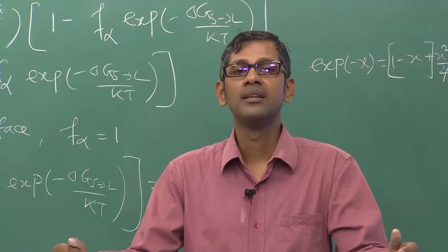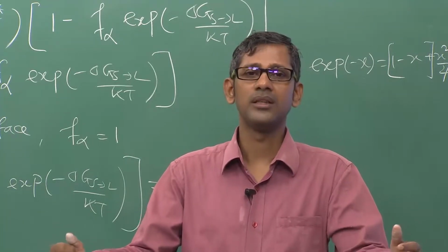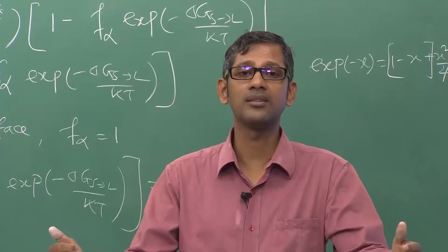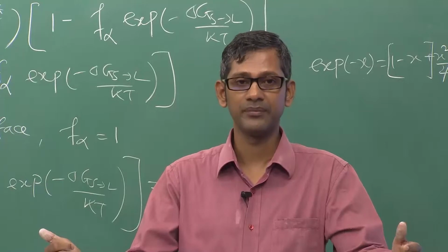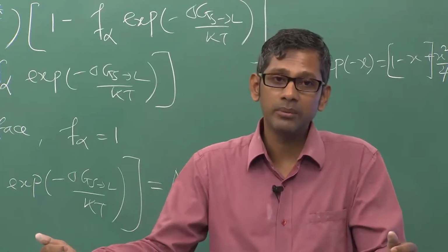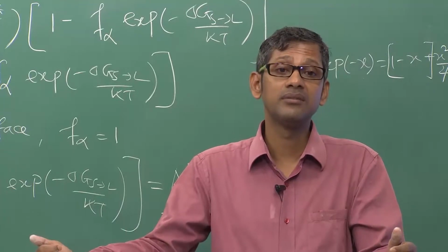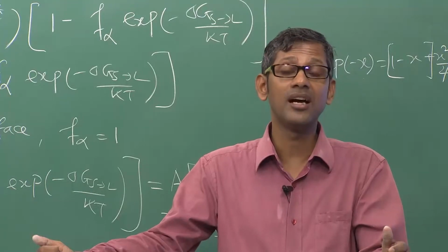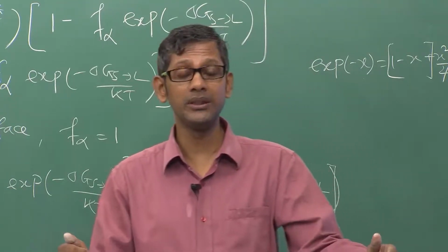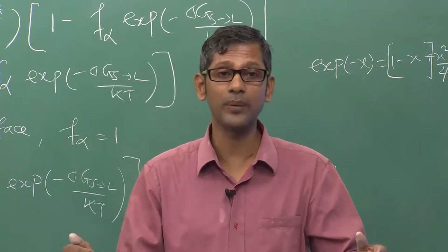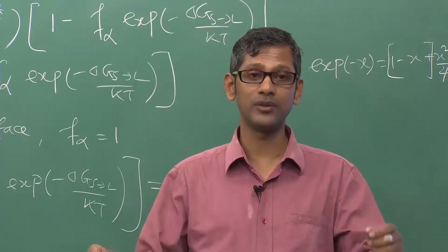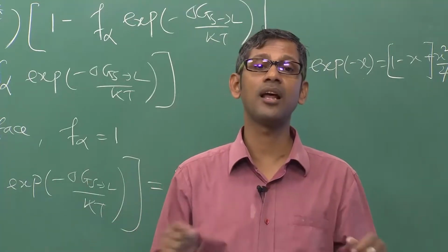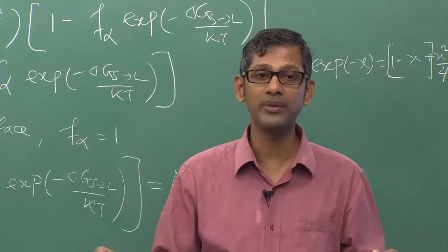It has not been discovered in one go. Basically it took about 50 years of research to understand how this growth happens. Okay, remember I have only talked about two different situations for the faceted interfaces. One is this nucleation on the surface to create a ledge, the other one is a dislocation. You can also have a twin situation. In the case of silicon, that actually happens: you can have twin re-entrant angles. You can have twins present on the surface, and these twins can allow the atoms to get attached. And that is what happens more in silicon.